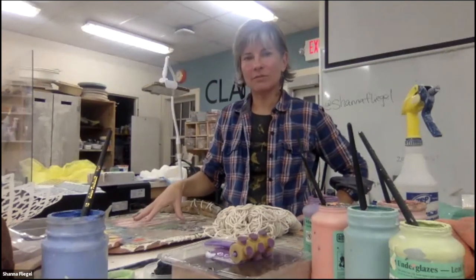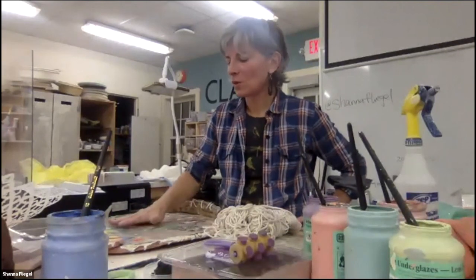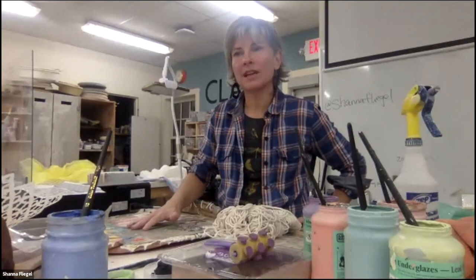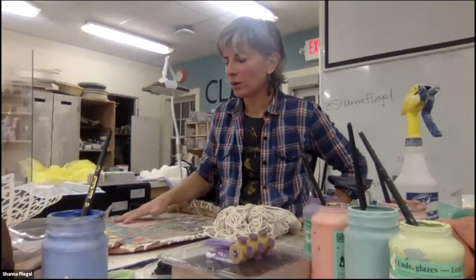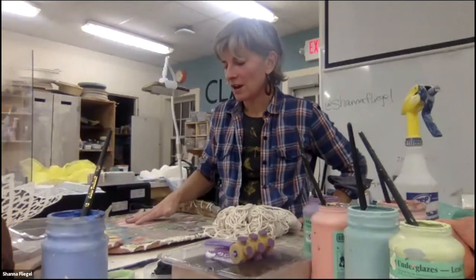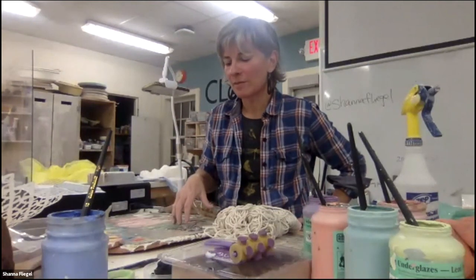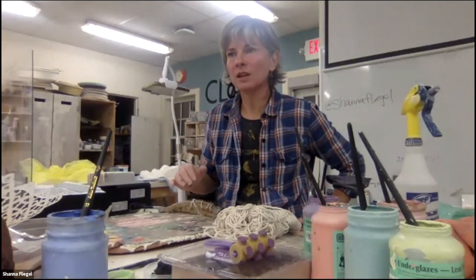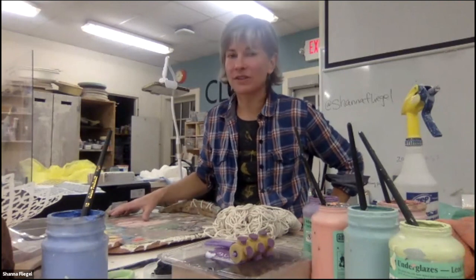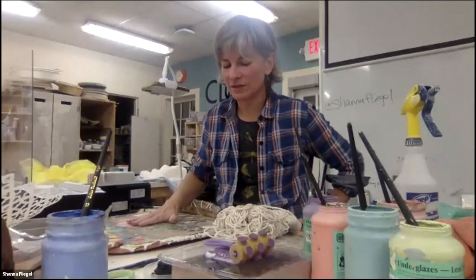Dry these really slowly in the beginning. And then when it comes time to do the glaze firing, I'll do an 04 to 1940 degrees and hold about 15 minutes at the end. Nothing fancy with the electric firing. But then the cooling, I don't do a controlled ramp hold down, but I will wait and make sure that it's like 150. Even then, all the shelves hold so much heat.